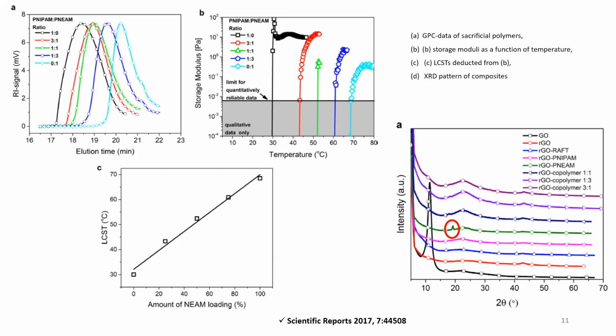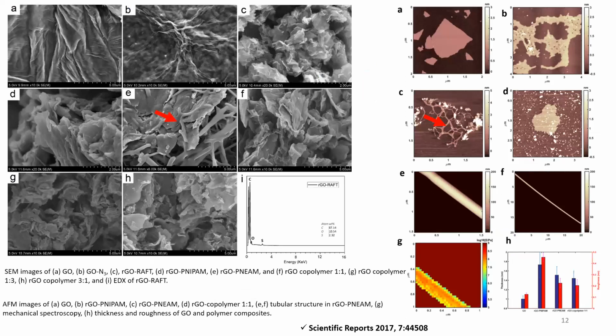But we noticed something quite strange in the XRD pattern shown on the right. There was this small sharp peak only in the case of the N-ethyl acrylamide homopolymer, but nothing crystalline was supposed to be here. In SEM images, we saw these tubular structures only in the case of N-ethyl acrylamide, as shown here on the left. AFM images show that these tubes are hollow with a Young's modulus of 80 megapascal. We speculated the mechanism of formation like this. Since N-ethyl acrylamide is more hydrophilic than N-isopropyl acrylamide, and the sheets are hydrophobic, the polymerization tends to make this repulsion and ends up rolling the graphene sheets.